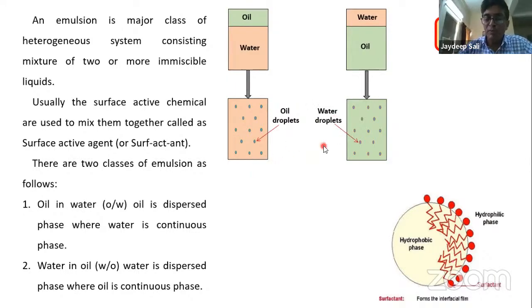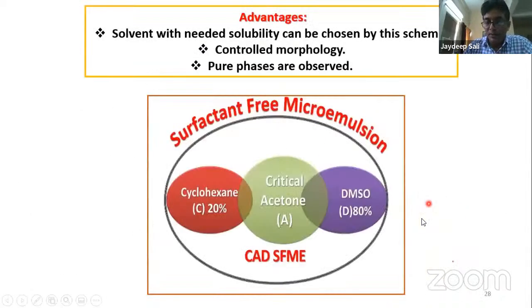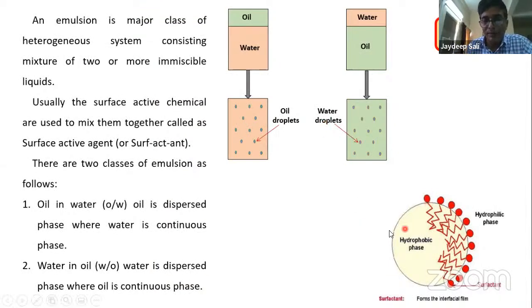We have formed this microemulsion without use of any surfactant, meaning without use of any such chemical like this. A surfactant is a chemical which forms a molecular layer on the hydrophobic phase like this, so that it can form a stable microemulsion. But the presence of these additional molecules, that is the surfactant molecules, can be a problematic thing for thin film formation. So therefore we try to avoid the use of the surfactant, and we form the microemulsion using a surfactant-free scheme.